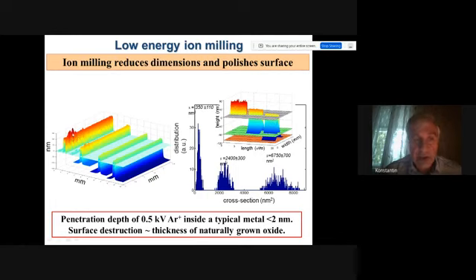And these imperfections are smoothed away during ion milling. This is the same effect as if you take a rectangular piece of brick and throw it on a sandy beach. After some time, let's say one year, it will no longer be rectangular, it will turn into some ellipsoid because sand polishes the sharp corners. So like this, we are able to reduce the cross-section and also to polish roughness.